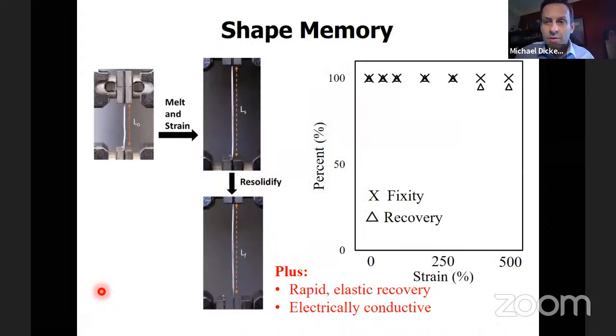So we use this for what's called shape memory. And the idea here is that you take a fiber and you stretch it. And once you stretch it, you freeze it. And so when it's frozen, you can then let it go. So this bottom part, you pull on it and then you let it go, and you measure what's called the fixity. That's how much of its original stretch length it keeps when you let it go. Because normally if you stretch something and you let it go, it goes back to its original length. But here we get about 100% fixity to very large strains. Then you take that and you heat it. And when you heat it,